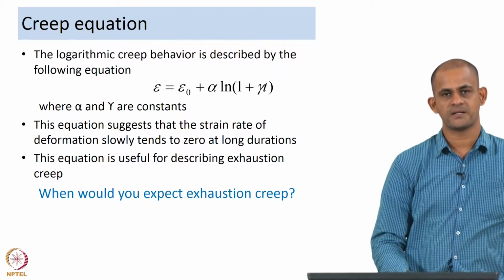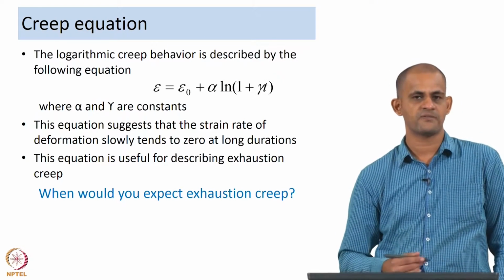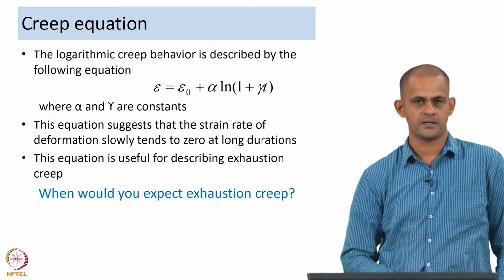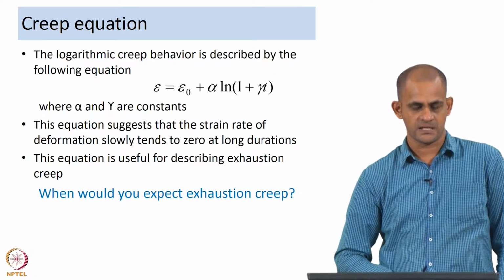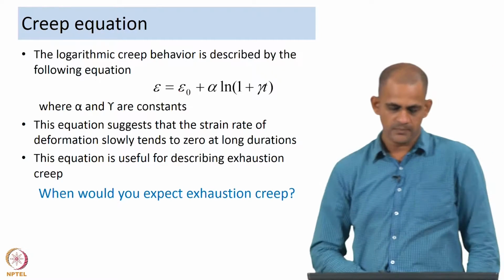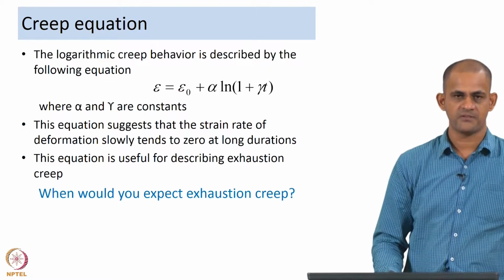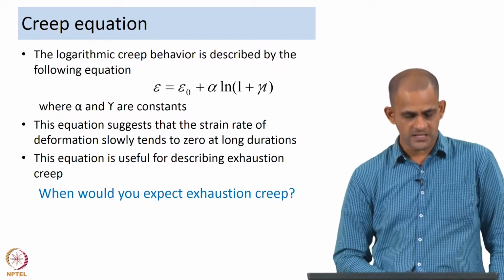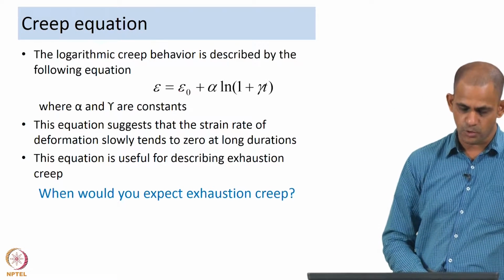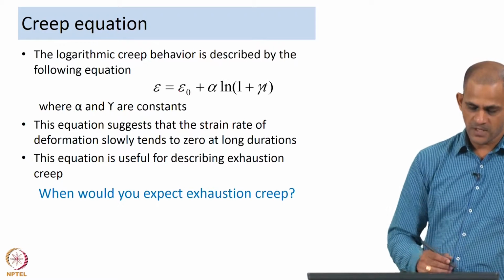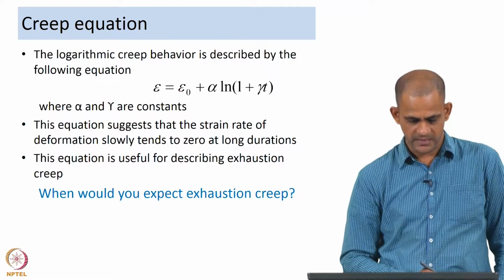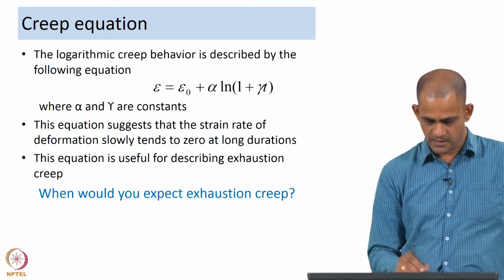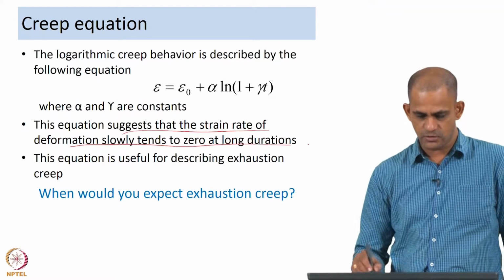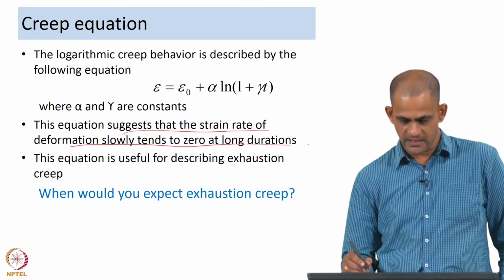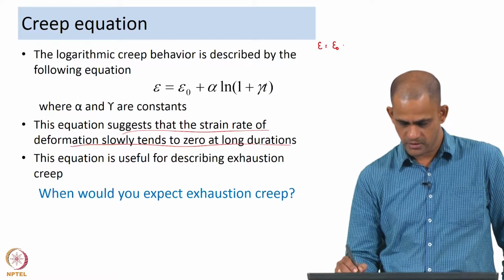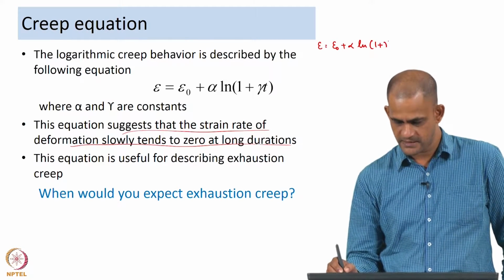However, there are other kinds of creep behavior, also creep equations, that people have observed. One such creep equation is the logarithmic creep equation. This equation is mentioned here. So, epsilon is equal to epsilon naught plus alpha ln of 1 plus gamma t, where alpha and gamma are constants. What this equation suggests is that the strain rate of deformation slowly tends to 0 at long durations. This kind of equation is useful for describing exhaustion creep. That is very clear if we take this equation, epsilon is equal to epsilon naught plus alpha ln of 1 plus gamma t.